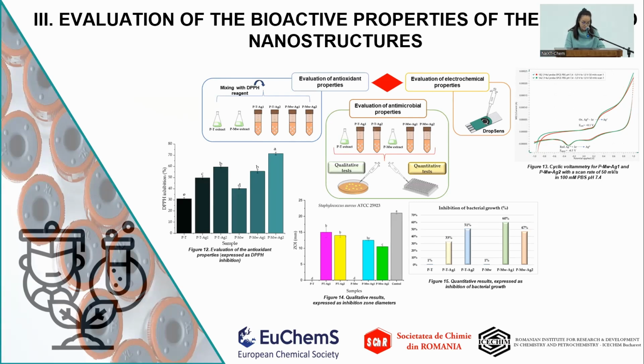The electrochemical profiles of the samples were similar, with an intense oxidation current present at the electrochemical potential of 0.1 volts, being higher in case of the ones synthesized in 1:2 ratio. Also, the reduction of silver ion takes place at the potential of minus 0.3 volts.